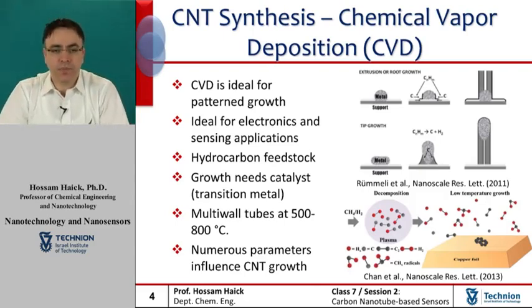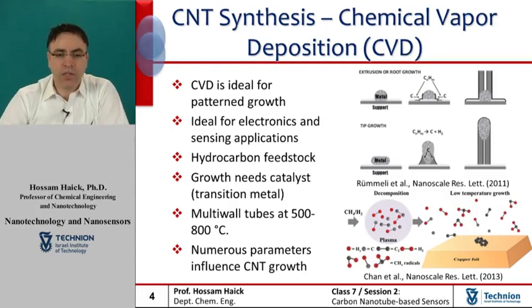In this case, the effective length for growing graphene between the plasma and the center of the hot zone can be examined. The optimal distance usually is in the range of 30 centimeters.